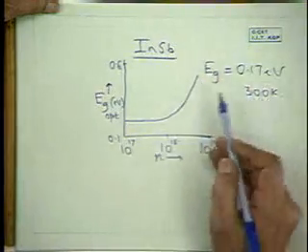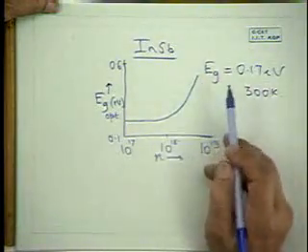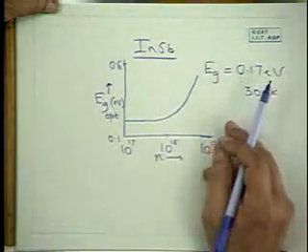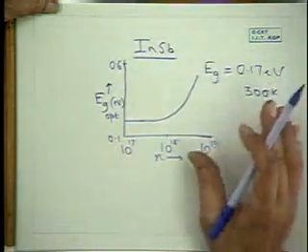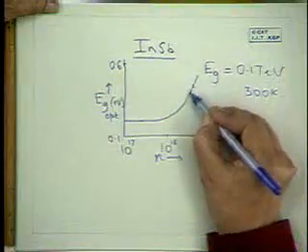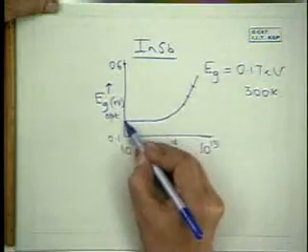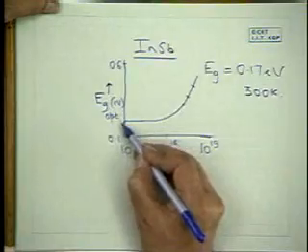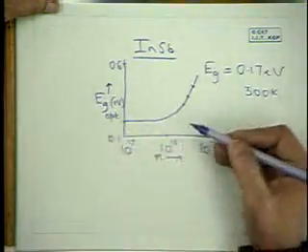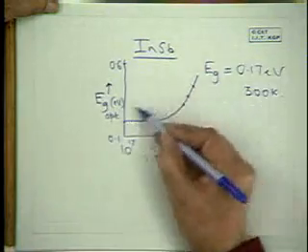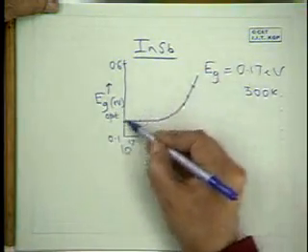So this is quite important historically, because when indium antimonide was first prepared, the impurity level was rather high, and the first optical absorption measurements gave band gap values around 0.4, 0.3. But it was only after indium antimonide was purified by zone refining and very pure material was prepared that one found that the band gap actually is 0.17. So if a material is impure, it has a lot of donors, especially, then the effective band gap measured optically is much larger than the actual band gap.